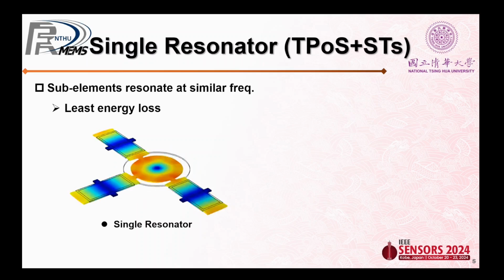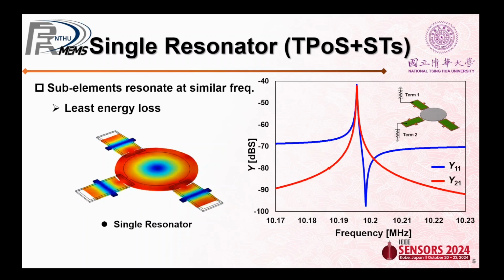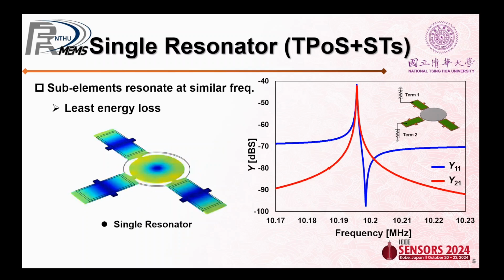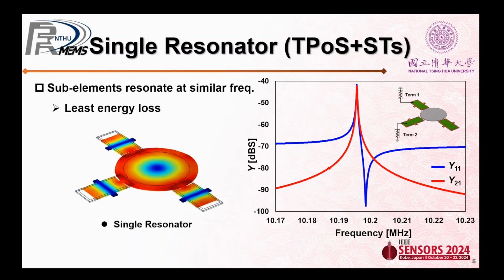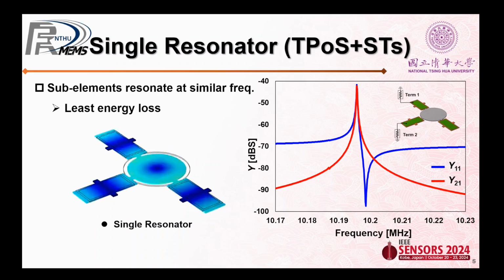Since the resonator in my research is a composite structure, it's crucial to ensure that each element operates at a similar resonant frequency. Finite element method simulations are used to analyze the response. The results show that after careful design of the sub-elements, the composite structure exhibits a resonant peak with minimal energy loss.